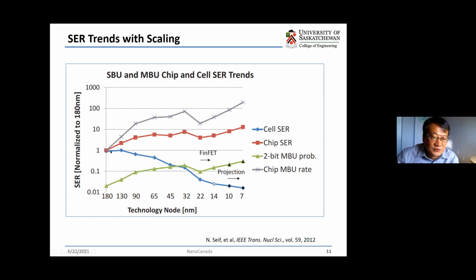And if we look at the chip level, the soft-error rate is also increasing because of this multi-bit upset. So it means that even if the device is getting smaller and the single bit cross-section smaller, overall at the chip level the soft-error rate is still increasing. So it means that we still have to figure out a way to deal with them.